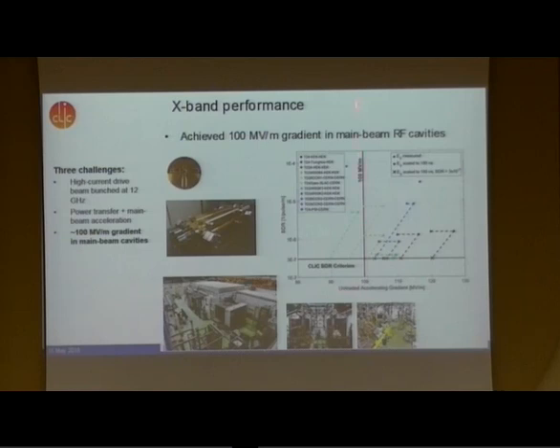And the relevant parameter is to look at the power we put into them, but also something called breakdown rate, which is arcing on the surface of these structures when you go to very high electrical fields. And this is an area where our Ukrainian collaborators have been very active to understand the different surfaces and what happens at the different surfaces for different electrical field and for different treatment of the copper in question. So I will not go into detail on that figure, but what you should note on the axis below, what is called the unloaded accelerator gradient, is that we reach around 100 megavolt per meter for all of these structures.